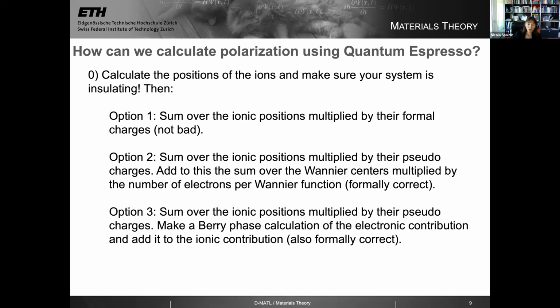The third option, which is also formally correct and is formally identical to option 2, is to sum over the ionic positions multiplied by their pseudo charges. That gives you the ionic contribution again. And then to get the part coming from the electrons, you can make what's called a Berry phase calculation of the electronic contribution. This is basically the same as the Wannier function contribution, but working in reciprocal space instead of real space. And some codes are more structured to make the Berry phase calculation more convenient than the Wannier construction.